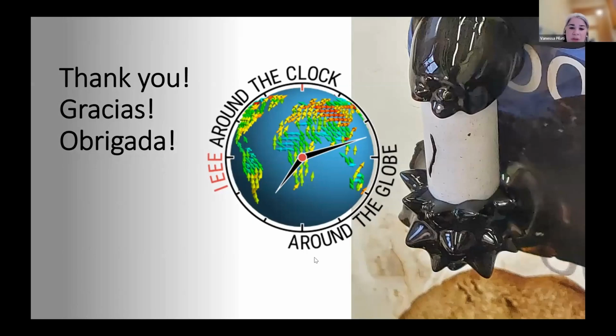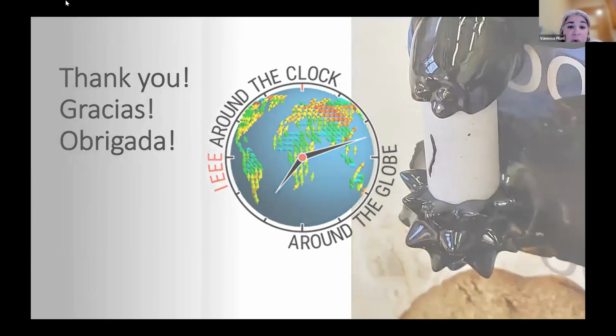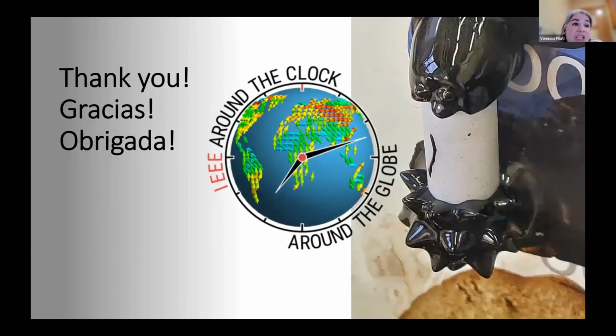Well, for commercially available tests, we don't have a magnetic test yet, as far as I know. For detection of gold nanoparticles, for example, we can use optical methods. We can take a picture, for example, with our cell phones, but it is difficult to have precision in this quantification, because any modification in the ambient light or the flash you use can modify the signal. So the standardization in this kind of tests is very difficult, but they exist. They are not very, how can I say, sensitive, but they exist.